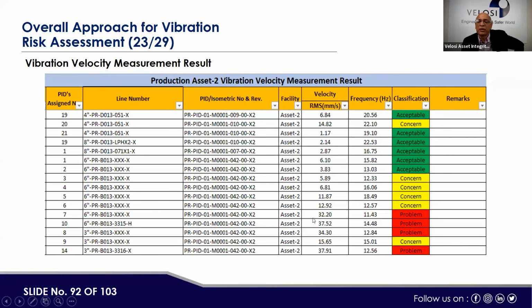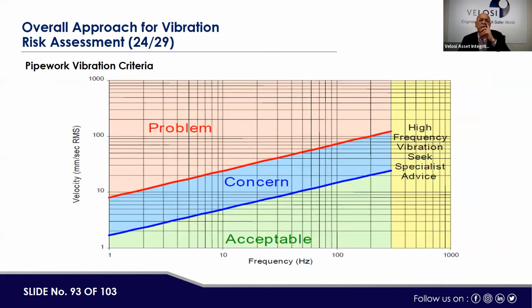Like here, other than the flare system, in the problematic area the velocity measurements were taken as 32, 37, 34, along with the frequency in hertz also 11, 14, and 12. So you could see that if velocity is lower, even if frequency is a little higher, that is acceptable. But if both velocity and frequency are higher, then it goes to the unacceptable range. So this was basically the criteria of the Energy Institute that we used: acceptable, concern, and problem, with velocity and frequency together.